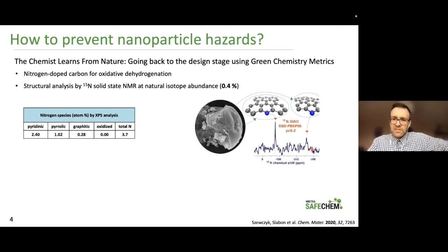And I will give you here one example. We have shown that you can use such a carbon catalyst doped with nitrogen in different positions, like pyridinic and pyrrolic, and it's also an efficient catalyst. And if you think about catalysis, why is it actually important to have such a material? We have shown it for the oxidative dehydrogenation reaction.